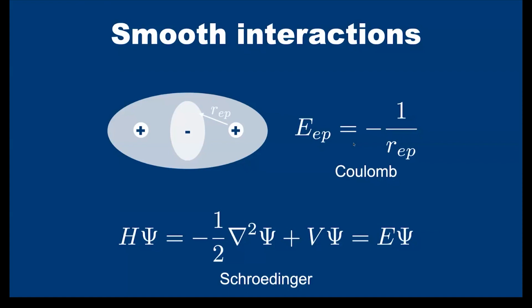They're not sudden little chinks in the energy landscape. They smoothly evolve. Now, that degree of smoothness depends on the particular bonding situation. So if you have a metal that is interacting through a non-directional metallic bond, that energy landscape is rather smooth. If you have a covalent system such as diamond, well, actually bonds are turning on and off in terms of the covalent bonds, and it's a much rougher landscape.